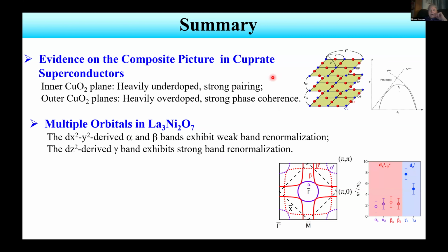Thanks a lot, Xingjiang. Again, this is related to a question, and look at these. You see strong Fermi surfaces, and then you wonder, where's the density wave gap? Because you saw from Liling's result, it looks like a large part of the Fermi surface is removed at the density wave transition. We had a similar puzzle when we were looking at Dan's original data on the 4-3-10, that they really weren't seeing much evidence of the density wave gap in the ARPES. Do you have any feeling for that on the 3-2-7?